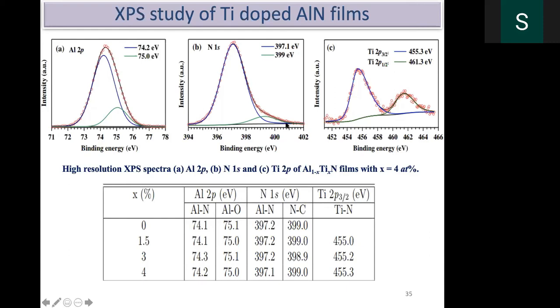And in the case of nitrogen also, you can see that predominantly it is aluminum nitride. Carbon is not there, because usually when you go to XPS, your fingerprints will also incorporate carbon. That is not the case here. So from this, we understood that aluminum nitride exists. For the titanium 2p 3/2 peaks also, we have seen an increase when you increase the titanium content, but this is very, very small.